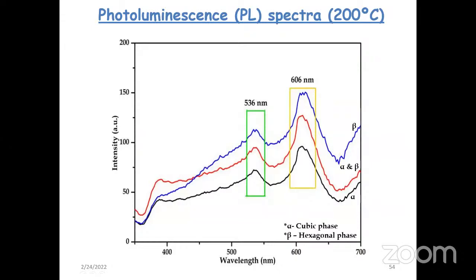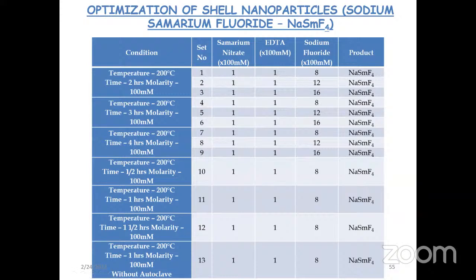Based on that, we went on to study the efficacy of photoluminescence, the light conversion efficacy. As you know, in upconversion nanoparticles we irradiate with near-infrared light, which is converted into UV-visible region light. We subjected the materials to photoluminescence, which shows that the mixed phase or the hexagonal phase shows better photoluminescence. We considered three phases: cubic, hexagonal, and mixed. We could find that hexagonal shows better, but in order to keep the size smaller, we sometimes go for a mixture of phases also.